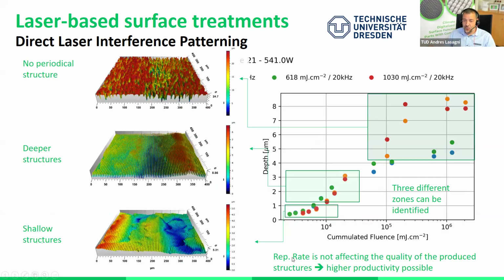So if we have to summarize this and put in some additional images, if we use less energy, we create the periodic structures, but they are not so deep. We can see the initial topography, let's say, after the polishing process. In the middle, then we have some deeper structure with high quality, and if the energy is too high, then we start to have overmelting and we destroy our topography.